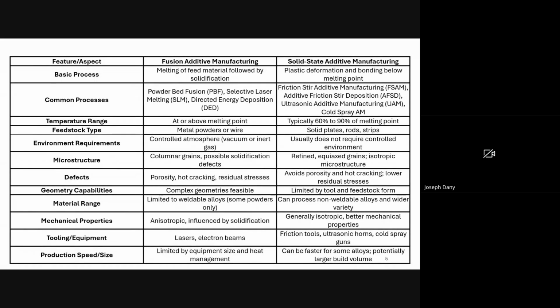In terms of material range, fusion is somewhat constrained to weldable alloys and sometimes only to alloys that can be atomized into powders, whereas solid state additive manufacturing can handle a much wider variety of alloys such as titanium, nickel, copper, aluminum, stainless steel, mild steel, and so on, including non-weldable materials. If we compare mechanical properties, fusion produced parts tend to be anisotropic, which means their properties vary depending on direction, while solid state processes give us more isotropic properties and often better overall mechanical performance.